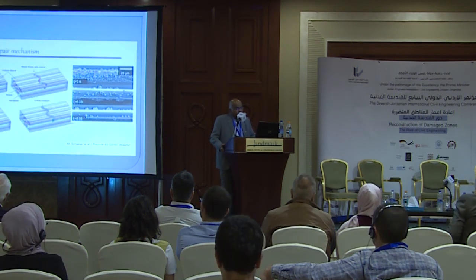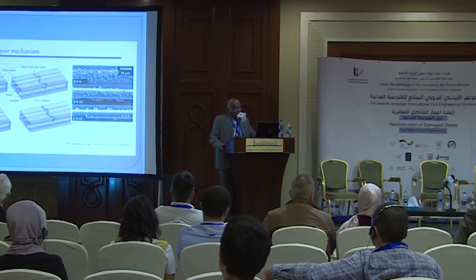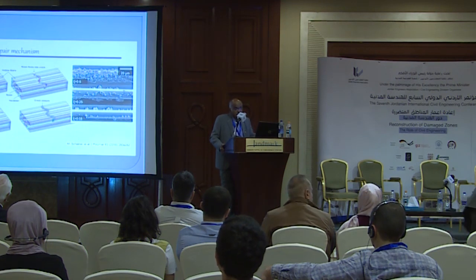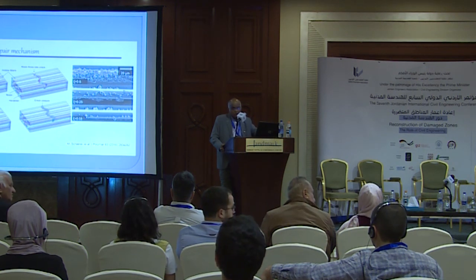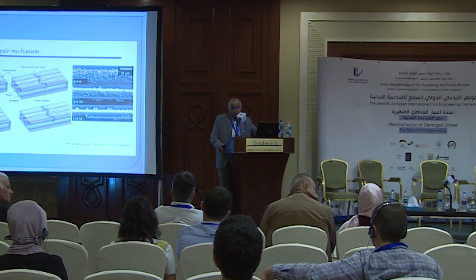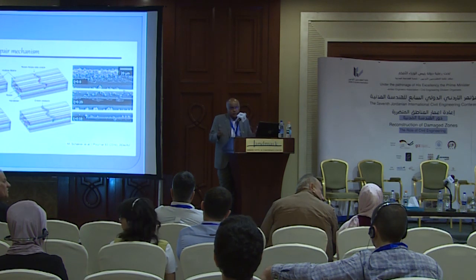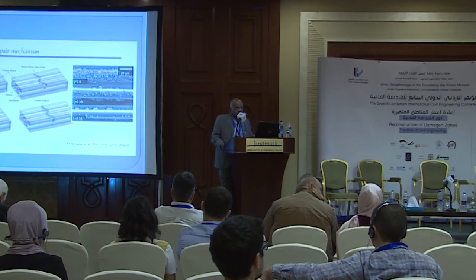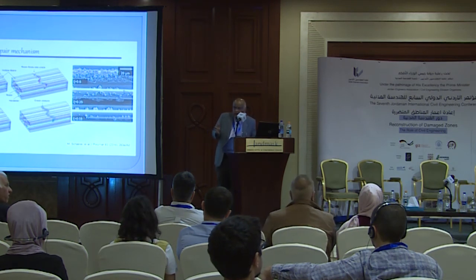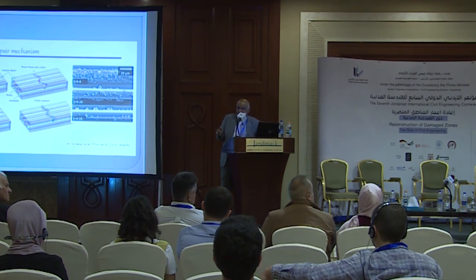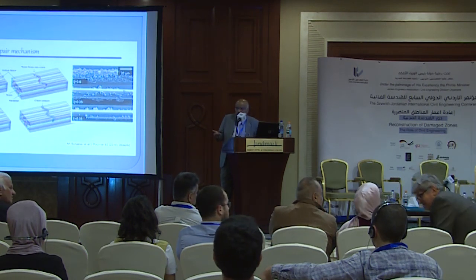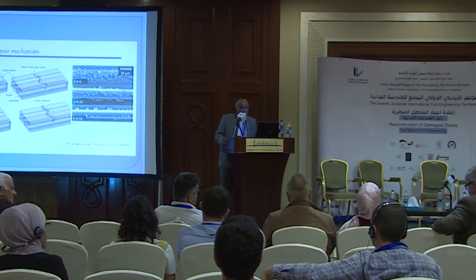So here is a better description. You have the crack in a, say, panel with hollow channels, and when the crack occurs, the liquid flows into the other hollow channels. It goes from the parallel channel without fluid, goes and fills it up and forms a bond. So it hardens and gives a strength to the material. And of course, you will not get 100% strength, maybe 80%, 70%, but it is okay. Instead of throwing away the material, you can keep on using it, you see. This is the idea.